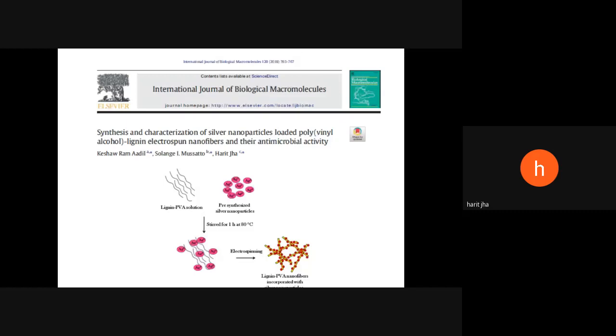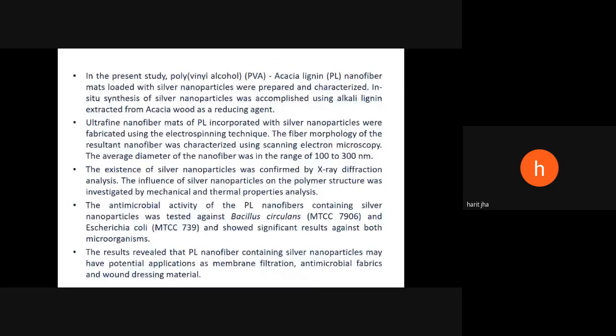So this electrospinning was carried out so that the lignin PVA nanofibers incorporated with silver nanoparticles can be synthesized. These ultrafine nanofiber mats of acacia lignin and PVA incorporated with silver nanoparticles were fabricated using the electrospinning technique. The fiber morphology was characterized using scanning electron microscopy, and the average diameter was in the range of 100 to 300 nanometers. The existence of silver nanoparticles was confirmed by XRD, and the antimicrobial activity of these nanofibers was tested against Bacillus circulans and E. coli and showed significant results against both microorganisms.